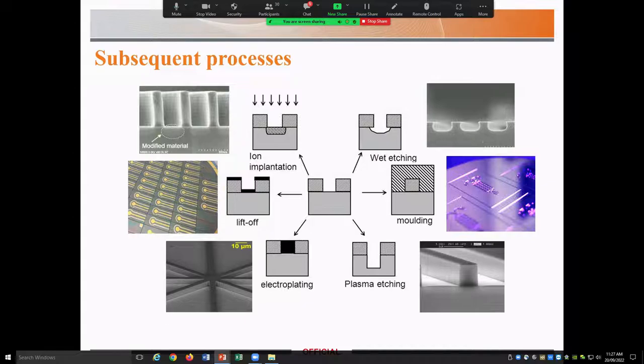The liftoff process is used mostly to generate patterns, like metal patterns and metal electrodes on the surface. The whole patterned wafer is coated with the desired metal, and then after we wash off the photoresist, we will have the metal pattern on the surface. The patterned photoresist can also be used in making masters and molds. A very common application is in PDMS casting, where the microstructure from a negative master can be transferred to polymer. I think there will be a practical session on this process as well.